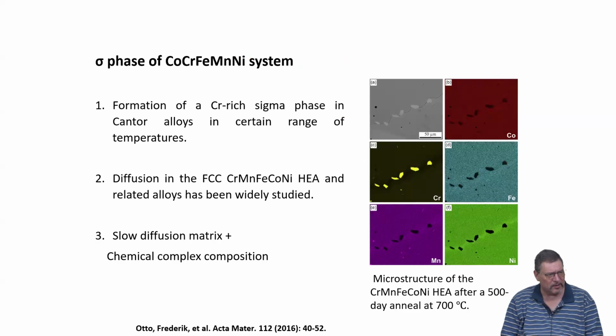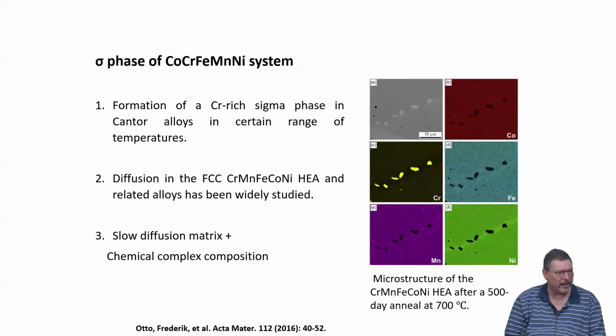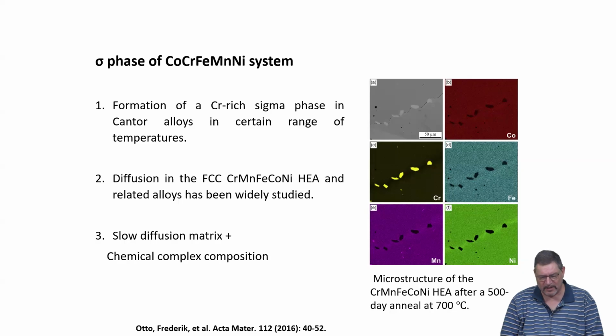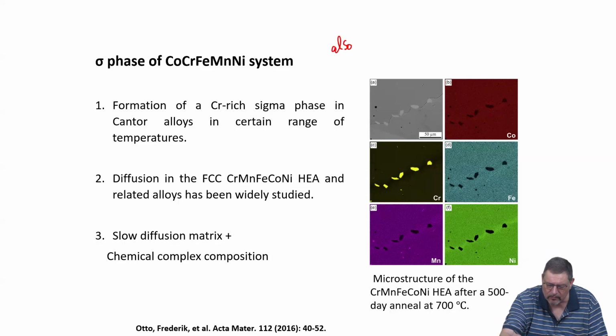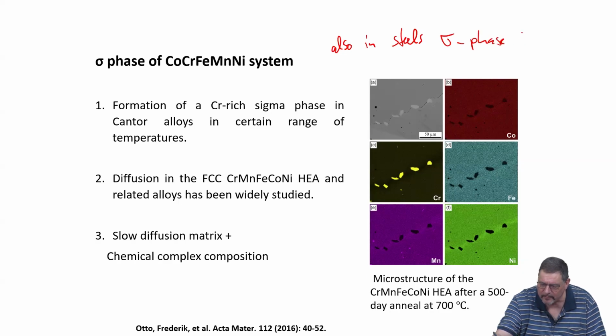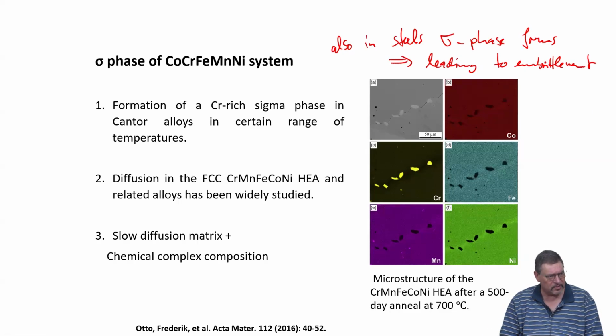And I will also talk about the so-called sigma phase in, again, the Cantor alloy. This is a chromium-rich phase, which forms at lower temperatures in the FCC model alloy Cantor system, cobalt, chromium, iron, manganese, nickel. And it is also normally, because it's known also to form in steels, a phase which you do not like to have. Because again, it's brittle, and that means sigma phase leads to embrittlement. So it's something which you normally would like to avoid in your microstructure.